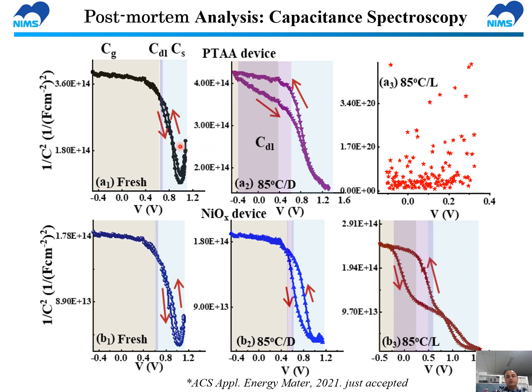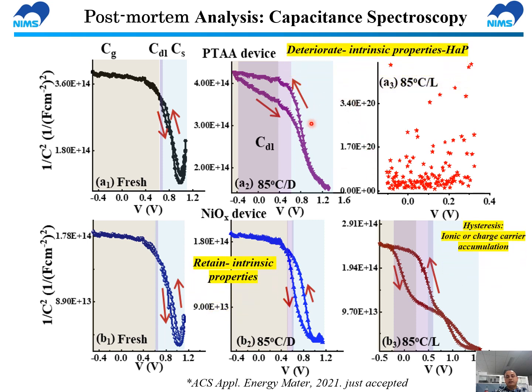And to have more insight into the optoelectronic characteristics of a degraded device, we compare the capacitance spectra of nickel oxide and PTAA devices, and we compare the phase under dark and under light. We can see this deterioration of intrinsic property for the device with PTAA. However, the nickel oxide device retained its intrinsic property, and we can see the hysteresis at higher temperature and under illumination. This could be due to deterioration of the interface with ionic or charge carrier accumulation at the interface.